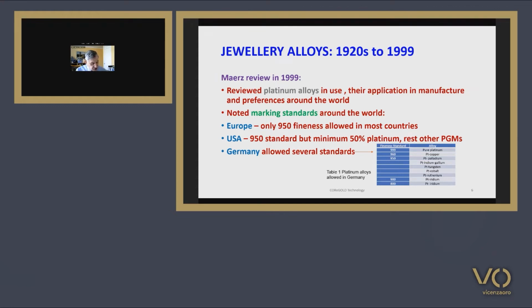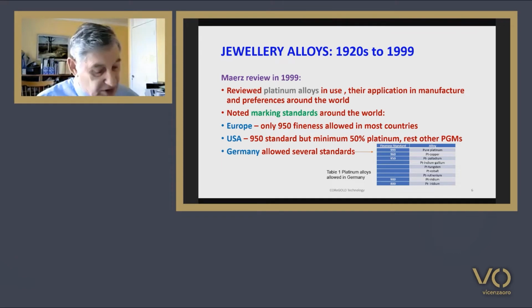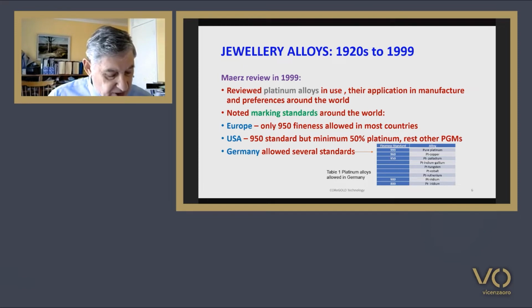Maerz noted European countries generally allowed only 950 fineness alloys, with some allowing no negative tolerance, some allowing a small negative tolerance, and others allowing iridium content to be counted as platinum within the 950 standard. In Germany, he noted that several fineness standards and alloys were allowed, as we can see in the table on the slide. In the USA, he noted that the standard for jewellery to be marked as platinum was 950 fineness, but the minimum amount of platinum allowed was 500 parts per thousand, with the rest of the alloy comprising the 950 parts per thousand total platinum group metals, and this with a zero tolerance. He also notes that 950, 900 and 850 fineness standards are allowed in Japan.